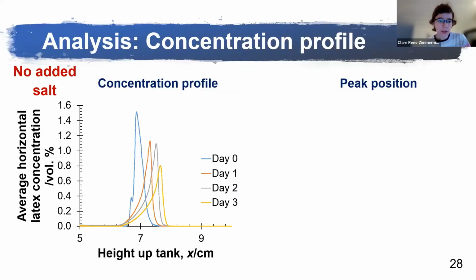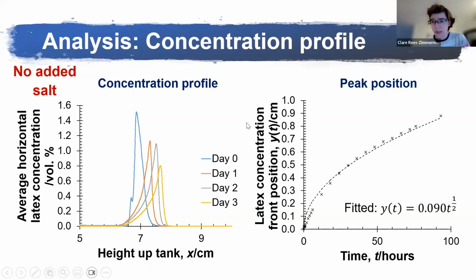Now I can analyze these images. I convert the latex intensity in the image to a horizontally averaged latex concentration. You can see profiles for day 0, 1, 2, and 3. For day 0, that's in blue, you see that there's an initial peak concentration at a certain height up the tank, and over time the position of this peak moves up the tank. I can plot the position of the peak over time. I've fitted t to the half as a guide to the eye. From theory, we don't quite expect a t to the half, but it's more a guide to the eye, and it suggests it could be some kind of diffusiophoretic process. The silica solution could be an error function, and then the latex moves in the silica gradient. But t to the half is a reasonable approximation to the solution.